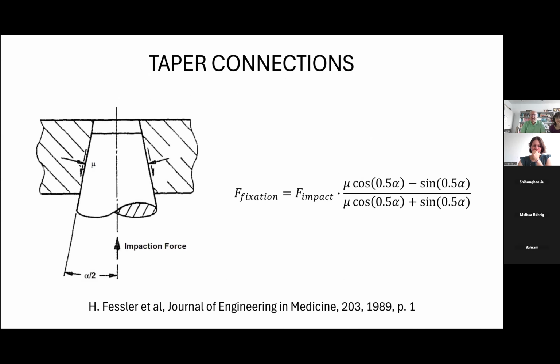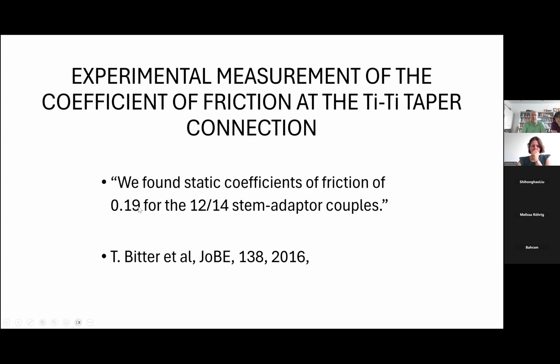And in order to minimize the micromotion that you have on the taper, I just took here a very old paper because it is easy to understand. I was working also for many, many years on this topic. And even if it is the first paper in this field, the conclusions of this paper are still valid today. You have these equations where you have the angle of the taper, you have the coefficient of friction at this interface, and in order to know the fixation, you have first to impact. And after, if you know the impaction force, you can calculate the fixation force, and the higher, the better, by definition, if you want to minimize the micromotion. But you need to know the coefficient of friction, and it is typically 0.2 for this type of connection.